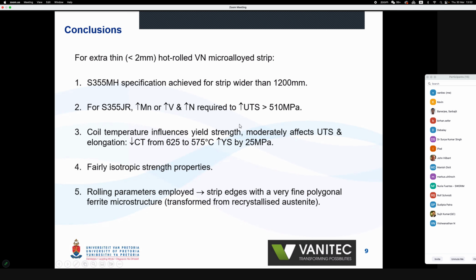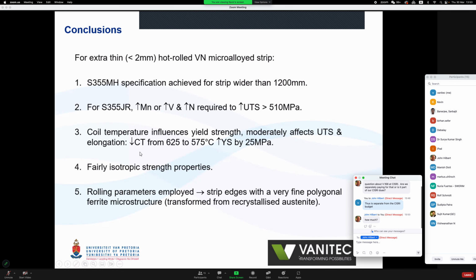Coil temperature definitely has an influence on yield strength, but only a very moderate effect on UTS and elongation. Dropping the coil temperature from 625 down to 575 increased yield by 25 MPa. We have also found fairly isotropic strength properties, transverse versus longitudinal, which was probably a good thing. And for the rolling parameters we are currently employing, strip edges have a very fine polygonal ferrite structure, which was transformed from recrystallized austenite.